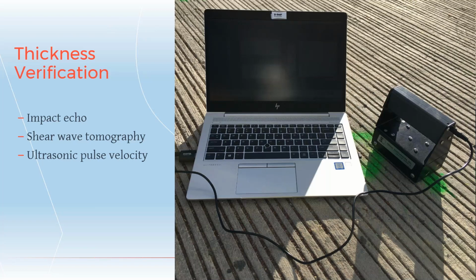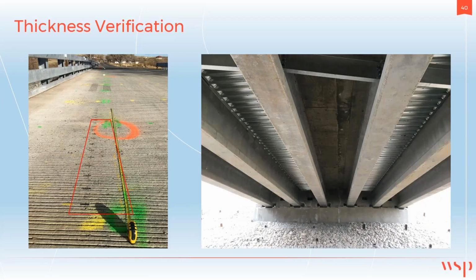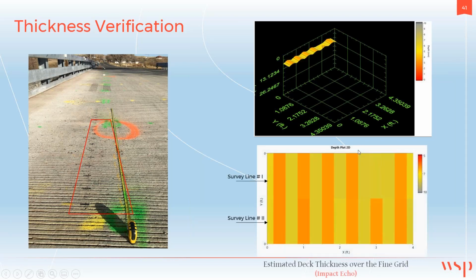For thickness verification, we can use any stress wave methods. This is the same bridge that we just saw. Looking at the bottom of the deck, you see that we have stay-in-place forms right here. We did an impact echo survey on a very fine grid just for thickness verification, and save for one spot, which would be this. Impact echo was quite accurate in detecting the top and bottom of corrugation.